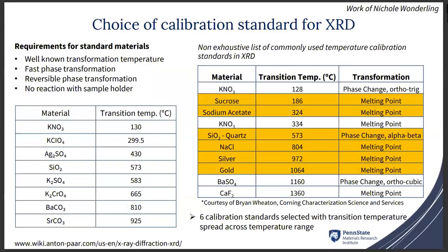For that we can use a standard material that has a well-known transformation temperature, a fast phase transformation. This transformation needs to be reversible, and it should have no reaction with the sample holder. What was used by Nicole for this study is six different materials that have sharp melting points or phase changes across the different temperature range this accessory can achieve.